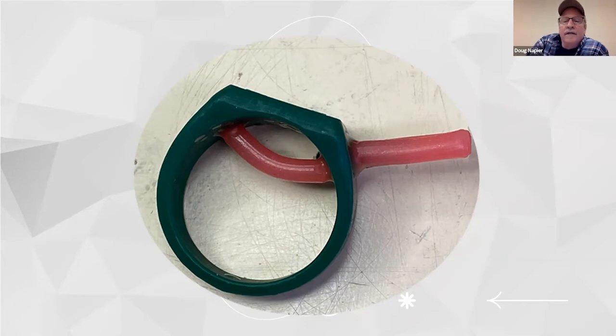So here I go in and sprue it from the thickest area, and also make sure that there's another feeder sprue to the other side. Otherwise, if I cast it, it's going to be clean on one side and the other side will have a little bit of porosity. So I want to make sure that I sprue to the thickest area. Now with wax, you can get away with one or two sprues, but with resin, I tend to really oversprue the piece. Any place in that piece that looks like it's going to be a problem area, I'll add sprues to it. I'll explain why I do that later, but you really want to think oversprueing when you're dealing with resin, because of that swell, and you want to relieve some of that pressure when the piece swells a little bit.